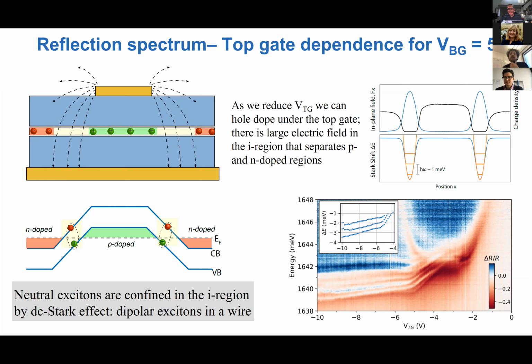We should see. And do you think one can thermalize these excitons so that you are actually getting closer to the ground state? Yeah, I think in principle, these experiments are reflection experiments with white light. So basically, we do not really create a high density of excitons and look for how they relax and form a thermal state or non-thermal state. In principle, yes, once the density is high enough, the thermalization time due to interactions will take over the decay. Of course, there are uncertainties, maybe Auger will take over before and not allow for true thermalization. It's hard to say, right?